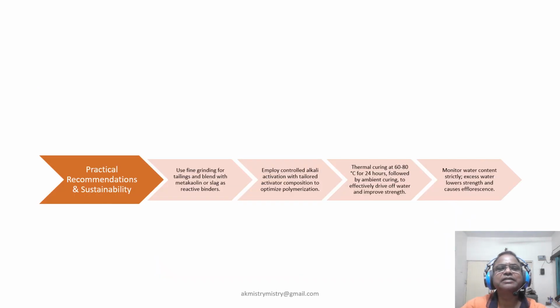Now, to ensure success in practical applications, a few recommendations stand out. First, grind tailing finely and blend it with a highly reactive binder like metakaolin or slag. Second, control types and concentrations of alkali activator to match the tailing composition. And third, apply a combination of thermal curing at 60 to 80 degrees Celsius for about 24 hours, followed by a period of ambient curing for strength growth. Strict monitoring of water content is very essential, and it also contributes a lot to the quality of the geopolymer. Too much water not only lowers the strength but also creates surface efflorescence, which affects durability.